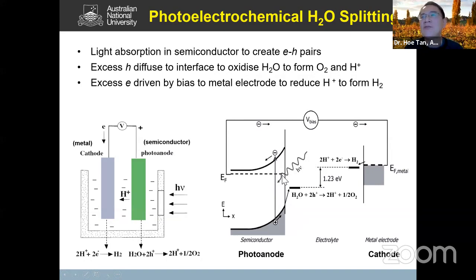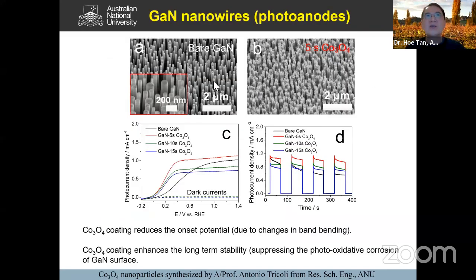And then now you shine light onto this, it creates these electron-hole pairs. And because of the band bending, the electrons are swept away into the external circuit by this external bias into the counter electrode to induce this hydrogen evolution reaction to occur. Okay? And similarly, on the other side, the holes are swept into the electrolyte to induce this oxygen evolution reaction to occur, okay? So I'll show you our results here.